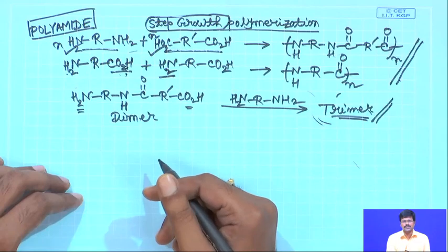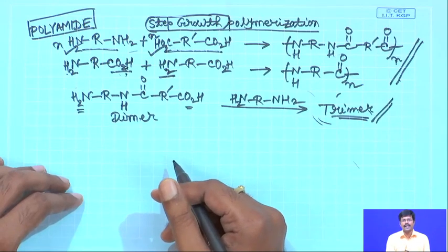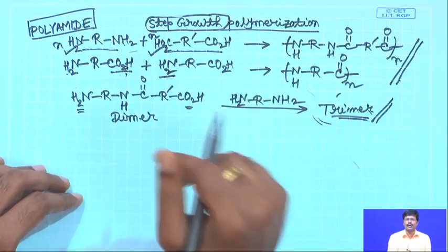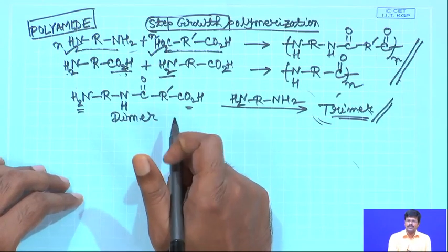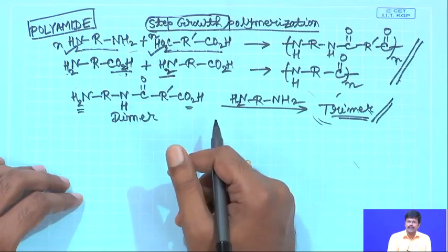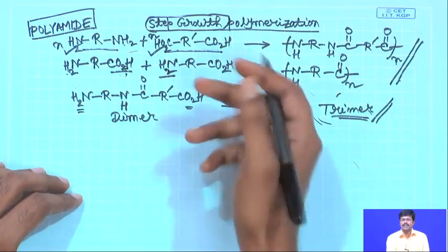95%, 96% conversion may be very good when you are reacting small molecules and preparing small molecules in your simple organic reactions, simple organic transformations. But say 90%, a conversion of 90% is a disaster in step polymerization, because you will have very low molecular weight polymer. We will discuss all these things. So you need to go beyond 98% of conversion, and you have to go sometimes beyond 99.5%, so on and so forth, in order to have high molecular weight, high enough that will meet your purpose.